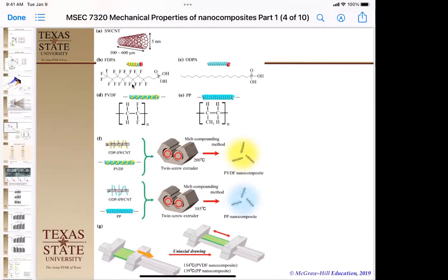In both cases, they take the nanotube that's been modified for that particular polymer system and do a counter-rotating twin screw extrusion to incorporate them. When they squirt out the nozzle, this is not a high enough shear to have them extremely ordered. They are hopefully really well mixed because we're using a counter-rotating twin screw extruder. But what that gives you is your nanocomposite as pellets. Then you take those pellets and press them into a sample right here, and then you heat the sample and pull it out a specific distance. That's how we get the draw ratio of 3 times the original, 5 times the original, or 7.